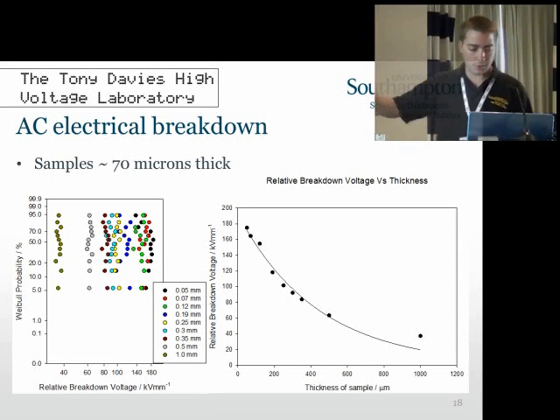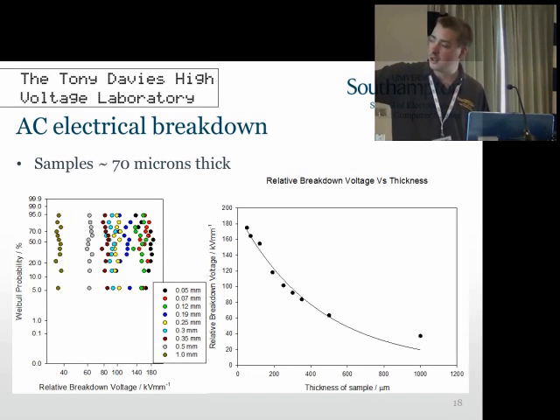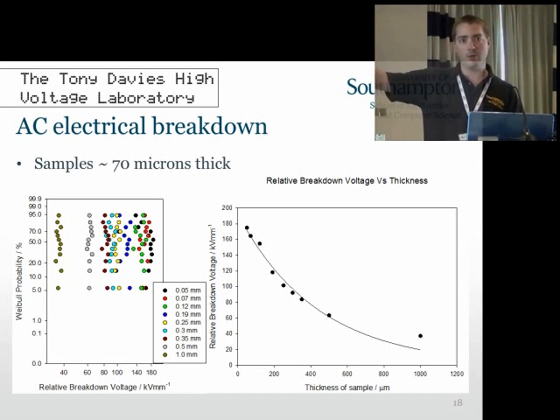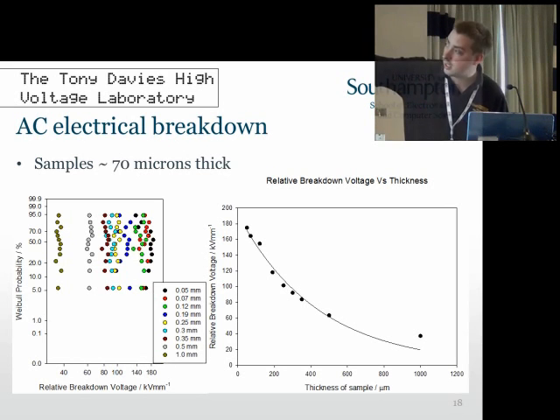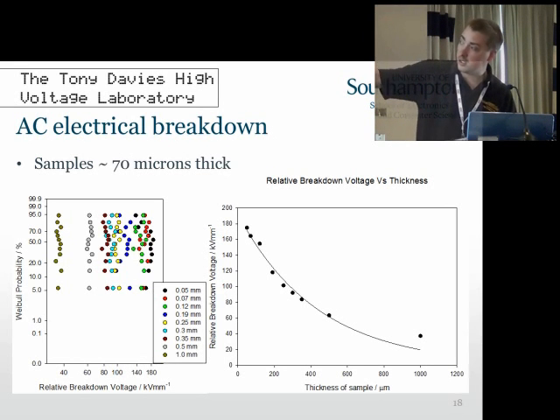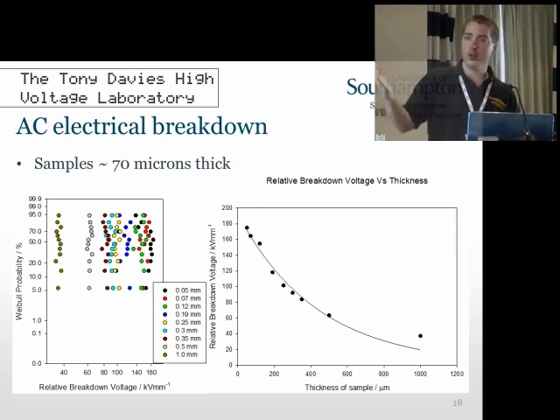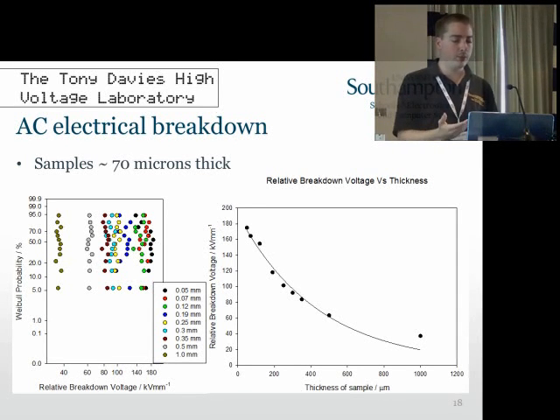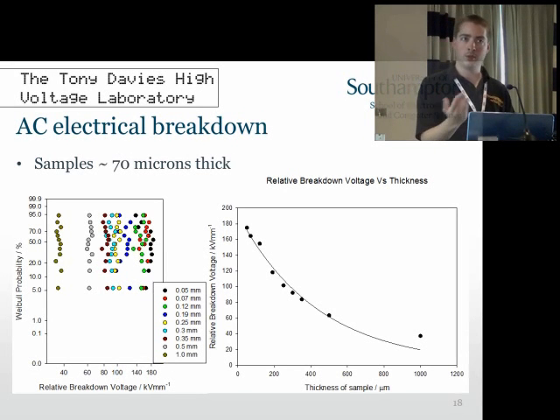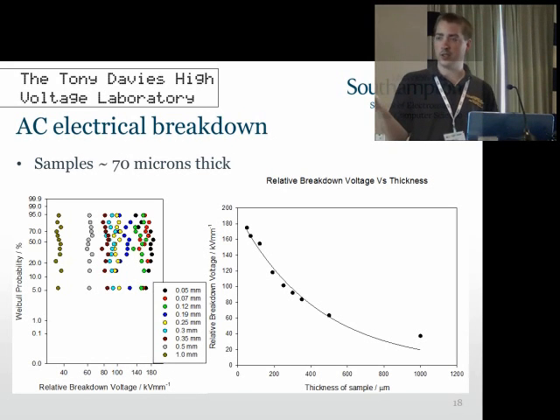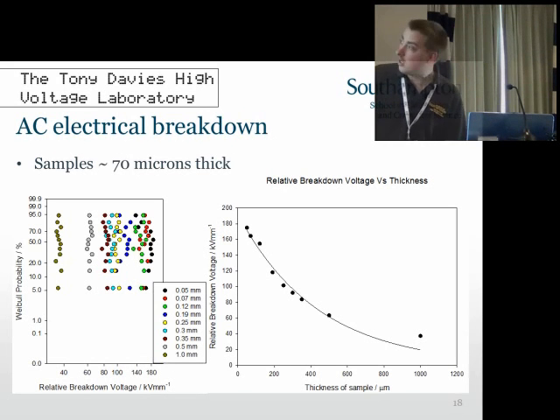You can see here, we'll jump straight to the right-hand figure. This just shows the thickness of your material just against the breakdown strength. So as you can see, as you increase your material, this is relative, so it's kV per mm as well. As you increase the thickness of your material, it becomes less effective as an insulator. Now obviously when you're producing samples and you're comparing the same thickness, this isn't a problem because you can still compare your samples. But when you begin to compare samples of different thicknesses, you have to take this into effect, especially at the high end here, where the gradient is very high.